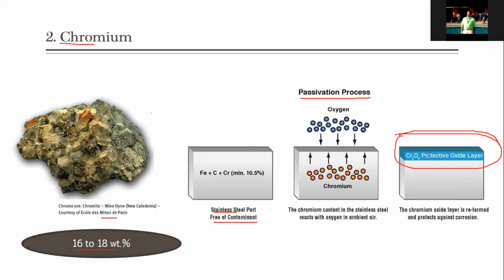The size of the passive layer will be around 0.1 to 2 nanometers. The corrosion resistance of any steel material depends upon this passive layer thickness, because it provides resistance to crevice and pitting corrosion. Hence this chromium content plays a vital role in the passivation process, that is, providing a passive layer on the surface of the steel.